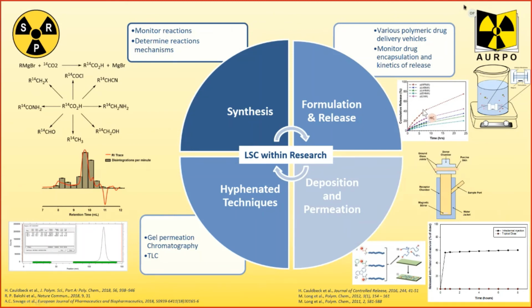So for example, here we generated a number of different polymeric nanoparticles containing a radiolabeled drug. We then used dialysis and took liquid scintillation counting measurements of the reservoir to monitor the release of the drug from the nanoparticles. So this graph shows how we got different rates of release depending on the polymeric material used within this experiment. We also look at deposition and permeation of radioisotopes through various materials.